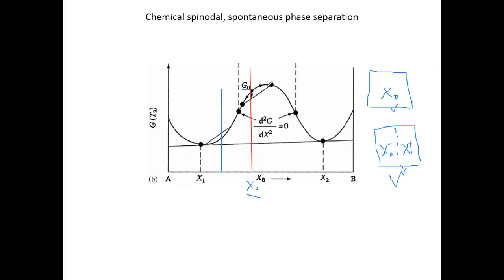Why is this the case? Well, if you follow this free energy curve, initially the free energy is right here, this dot. But if you separate into two different compositions, the lower composition is going to have a free energy right here, and the higher composition region is going to have a free energy here. And we know from the construction we have discussed many times that if you take this system and this system and literally glue them together to form an overall system in the phase separated state, the free energy of the whole system will be a linear combination of the free energy of each of the pure systems, right? You construct a straight line connecting these two free energies, and this intersection gives you the free energy for this phase separated state.